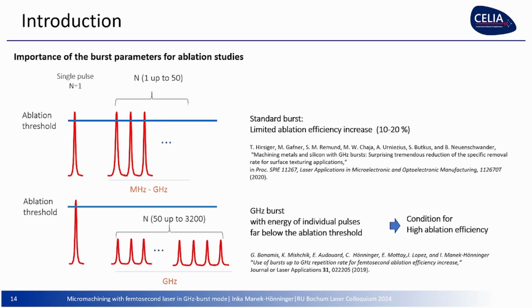So, why this? He was working in a regime, repeating the pulses at megahertz to gigahertz, but each individual pulse was operating above the ablation threshold. That means already with the first pulse, you ablate. And then in metals, depending on the repetition rate and the material, heat diffusion and the specific ablation rate of this metal, you could even see with the first pulse you're ablating, and then with the second pulse almost nothing works. There's nothing ablated.